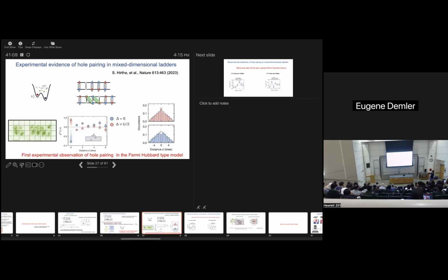And so, if we take a plain vanilla ladder, then actually we're less likely to find two holes on the same rung. So in this regime of temperatures, some call this kinetic energy dominant, and therefore we do not get binding. On the other hand, when this kind of imbalance is added, which makes exchange interaction strong, then we immediately find a large increase of the probability of finding two holes on the same rung. So we find very strong hole bunching.